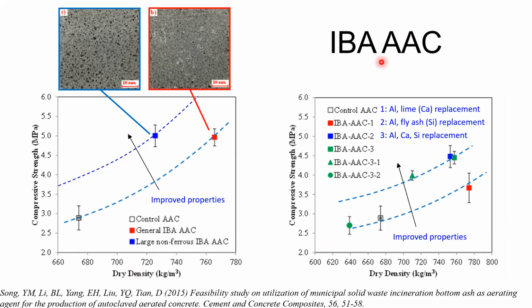There's another attempt where we combine different combinations using lime replacement, fly ash replacement, and aluminum or calcium silica replacement. We also observe improved properties in terms of the compressive strength to density ratio.